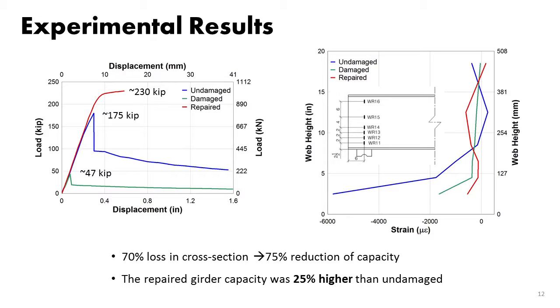And on the right, you can see the distribution of strains along the height of the girder. The blue one is, again, intact. And on the green one, you can see all the strain was concentrated at the bottom. The red one is the important one here. That shows that after we apply the repair, the concrete cast takes all the stress off of the web, and the forces are carried by concrete, essentially. One of the questions probably will be, what if corrosion continues after we apply the repair? Let it happen, because we have taken the forces out of that portion.